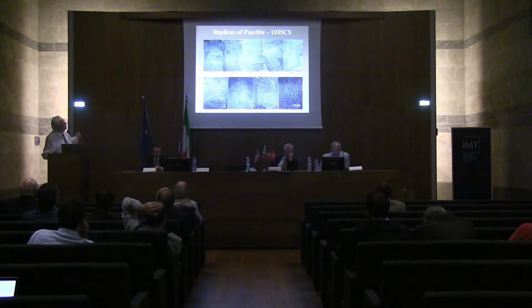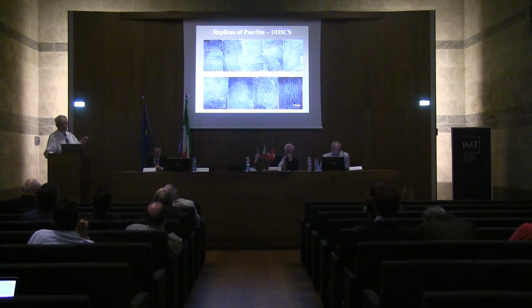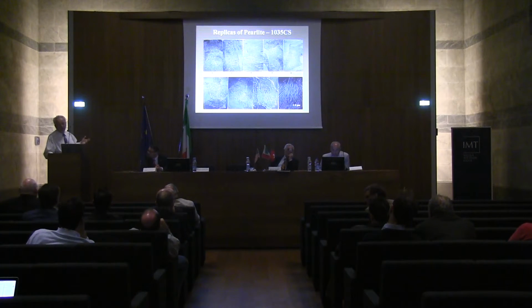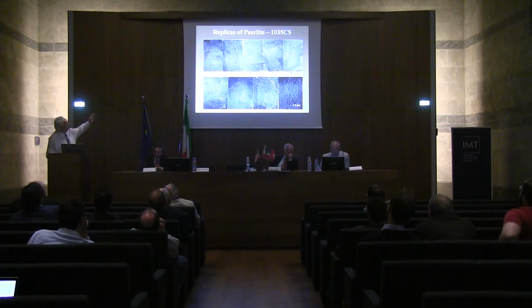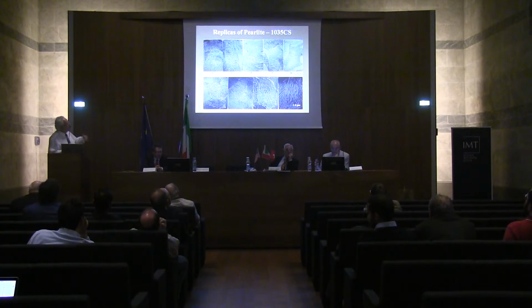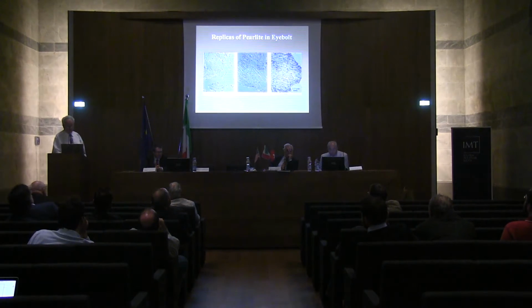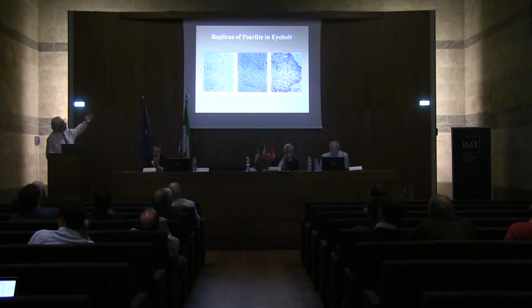Another thing I did was look at the interlamellar spacing of the pearlite. Here are examples of carbon replicas of the pearlite viewed in the TEM, because we need high enough magnification to resolve all the lamellae, and then we can do spacing measurements of the lamellae. You can see as we go to slower and slower cooling rates that the lamellar spacing is increasing, which is exactly what you'd expect. And here are results in the eye bolt, surface, mid-radius, and center. Those are fairly coarse spacings at the same magnification as the previous.